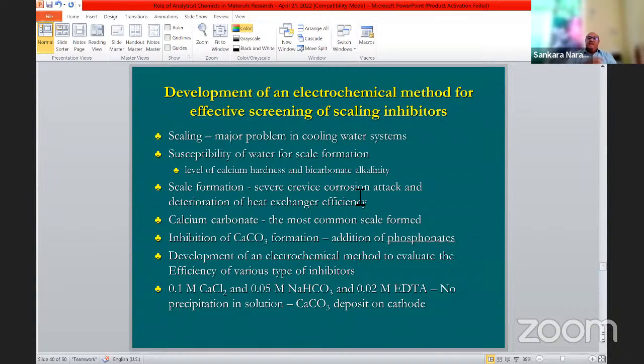In the same solution, you can add scaling inhibitors. People are selling scaling inhibitors, or you might have developed a scaling inhibitor which could inhibit scale formation. If you add that inhibitor into the solution, you can measure the amount of calcium carbonate deposit formed on the cathode by weighing. Initially you weigh the cathode sample, and after depositing for a particular period, say 3 volts for 60 minutes, you wash it, dry it and weigh it. So you know how much calcium carbonate is deposited. In the same solution, if you add different concentrations of a scaling inhibitor, you can find out how much calcium carbonate is forming. Based on that, you can fix the optimum concentration of the inhibitor you are developing, or whether the inhibitor is efficient or not.